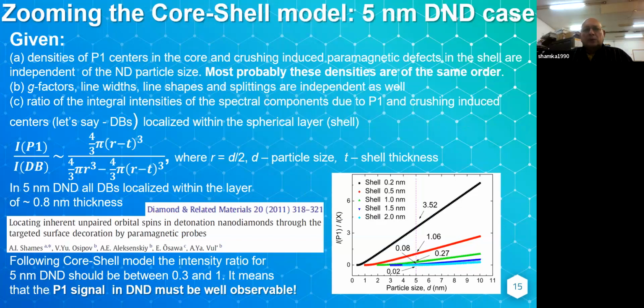Let's look at the core shell model more carefully and try to apply it to the 5 nanometer nanodiamond case. What is given? Densities of P1 centers in the core and crushing-induced paramagnetic defects in the shell are independent of nanodiamond particle size. Most probably these densities are of the same order. G factors, line widths, and shapes are independent as well. This is the main point of all these core shell explanations. Then one can calculate the ratio of integral intensities of the spectral components due to P1 and induced centers using a very simple formula, and then analyze them.